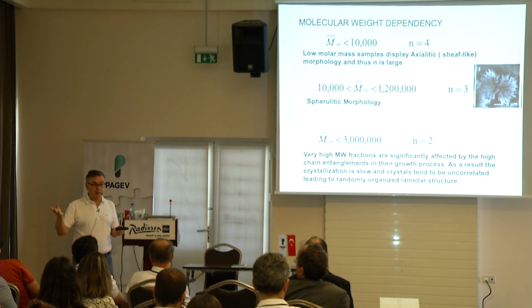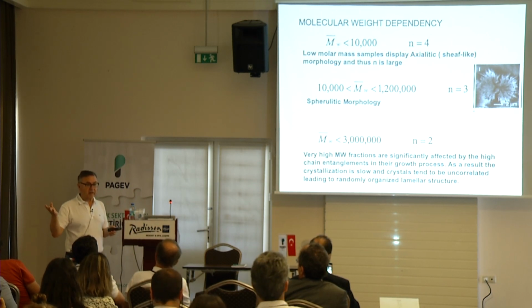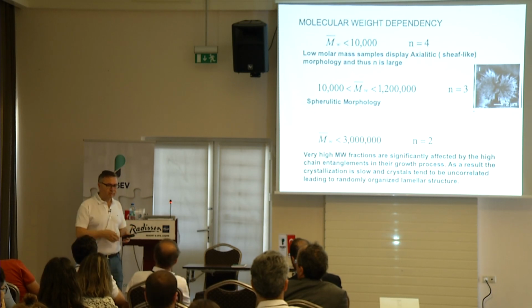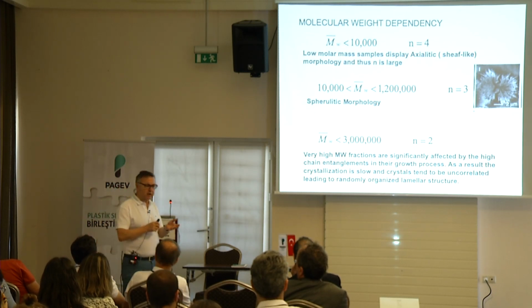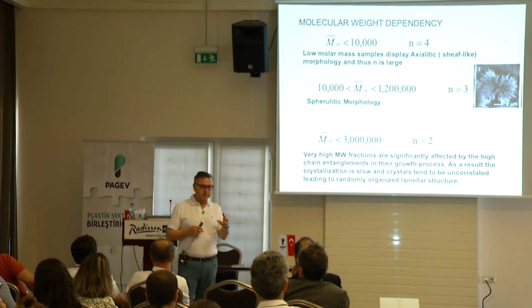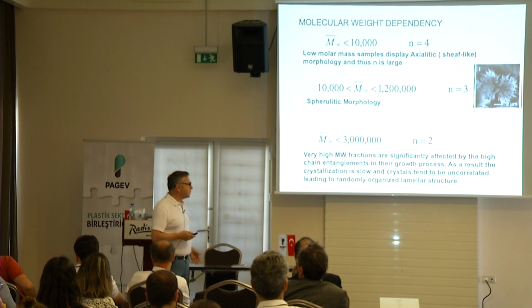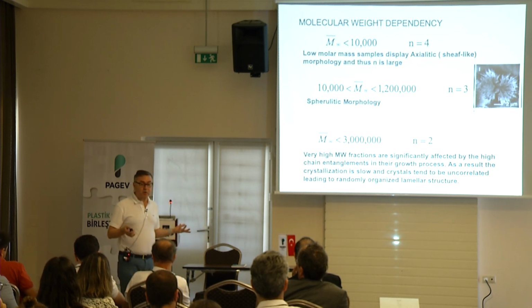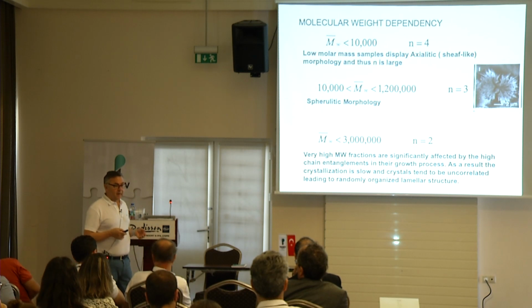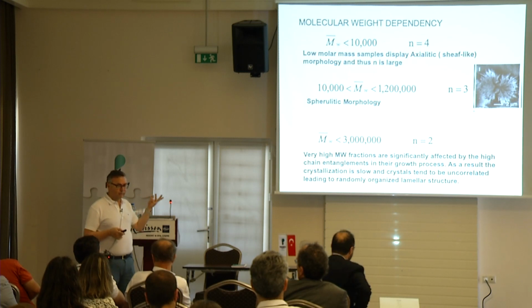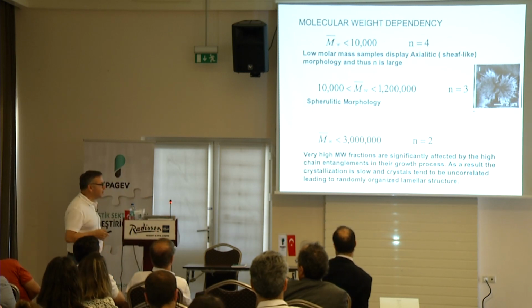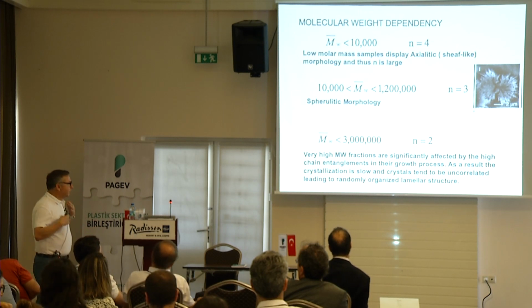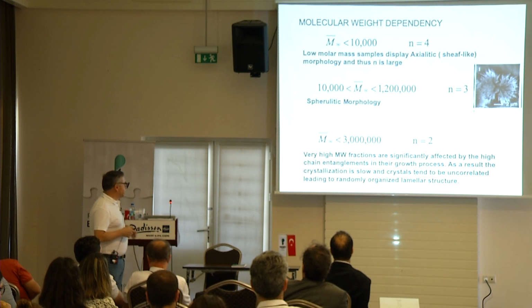Ultra-high molecular weight polyethylene is a great material, fantastic material. It's cut resistant. The reason it's cut resistant is that it has such a high density of entanglements. It doesn't cut. I don't know whether it's in the Turkish market, but the gloves for butchers are cut resistant. They use those. It's an ideal material. But you cannot use it for super high performance systems or high temperature applications. At the end of the day, it's polyethylene. It's going to melt at 140 or so centigrade, so it's not an engineering material. But they still use it for armor suits and things like that.